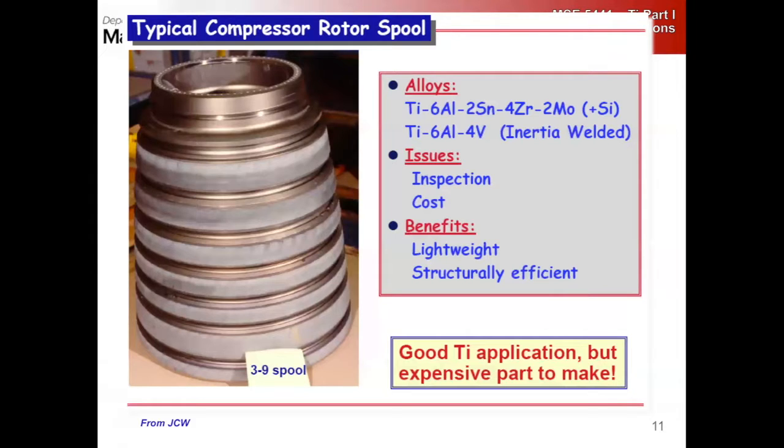Solid state welding technologies like inertia welding were pretty big. Inertia welding essentially holds one piece still and you push the other piece next to it and spin it really fast. Then you get them both really hot by frictional forces, and you get plastic flow that squeezes all the interfacial gunk out. Then you stop it really fast and a solid state joint forms. But you never get it hot enough to melt, so you don't have any melt defects in there.